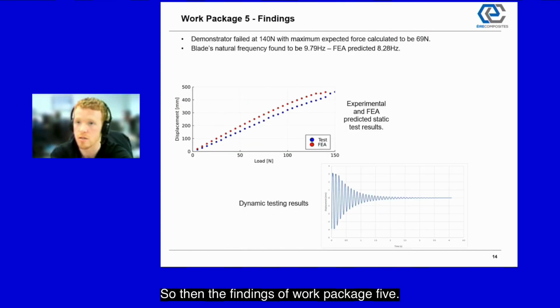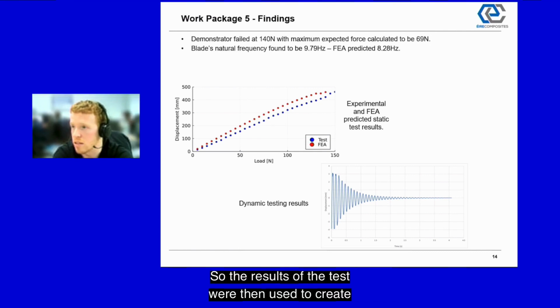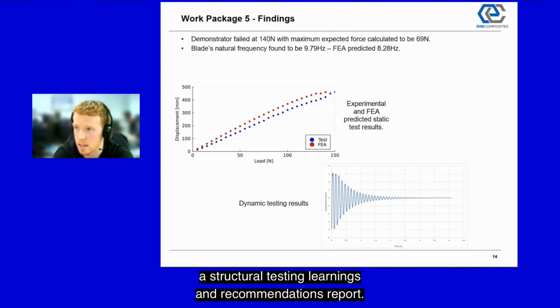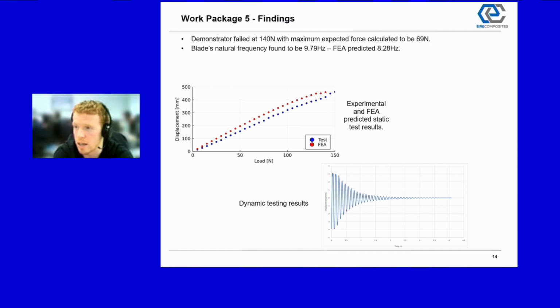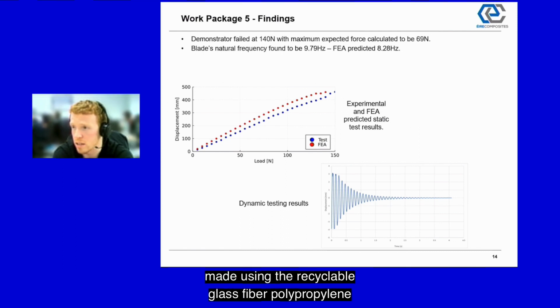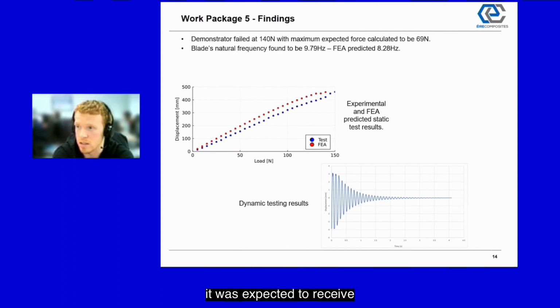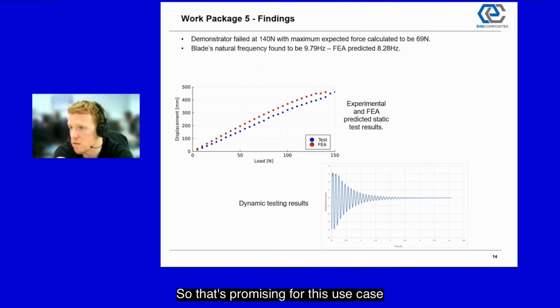So then the findings of work package 5. The results of the test were then used to create a structural testing learnings and recommendations report. From the mechanical testing performed on the 1 kilowatt blade, it was found that a blade made using the recyclable glass fiber polypropylene could withstand the maximum loads it was expected to receive, and the blade fails at approximately 140 newtons, with the maximum force it is expected to receive only being 69 newtons, so more than twice the load it can take. So that's promising for this use case.